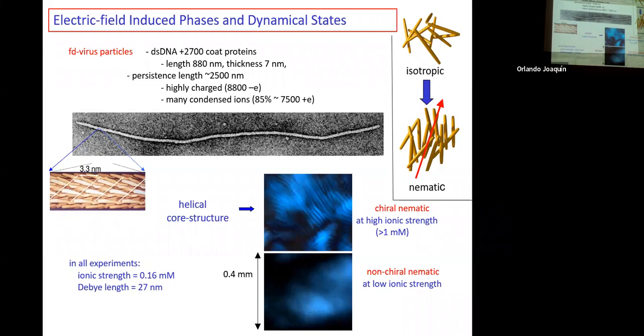That is due to the chiral core structure, but you only see this structure if the ionic strength is high enough, so that the thickness of the double layer is small enough that the rods can approach each other and feel this twist force. If the ionic concentration is low, the extension of the double layer is large, so they repel each other over a large distance and do not come sufficiently close to produce this chiral interaction.